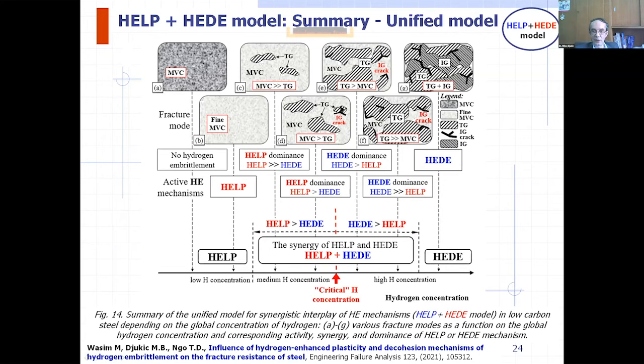But we have initial HEDE mechanism activation within the predominant HELP mechanism activation in the form of transgranular fractured area and also intergranular cracks in specific microstructure. During further hydrogenation of the material and reaching of the critical hydrogen concentration, as you can see, the transgranular and intergranular fractured area becomes dominant. We also have remaining areas in gray due to the HELP mechanism and microvoid coalescence area, while in the case of supersaturation, we have almost exclusively brittle fracture due to intergranular and transgranular fractured area, as shown in this picture.